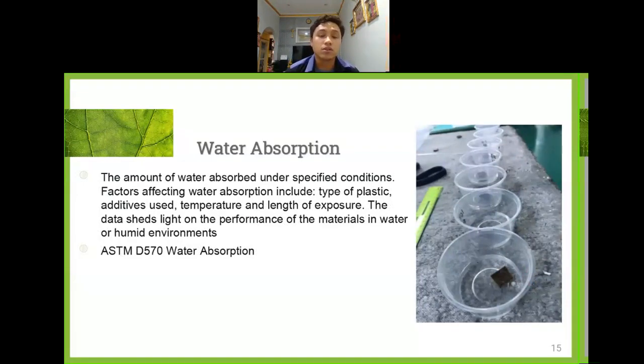Then we go to the next one. I use a water absorption test. This is the amount of water absorbed under a specified condition. Factors affecting water absorption include type of plastic, additives used, temperature, and length of exposure. The data shed light on the performance of the material in a humid water environment. This one I follow the ASTM D570 for the water absorption test.